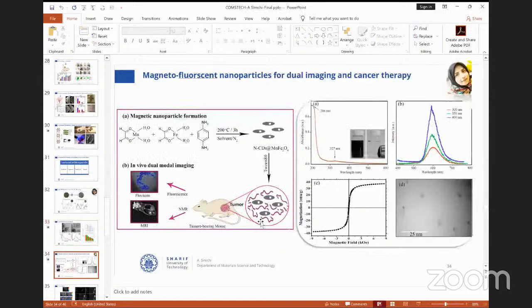Therefore, we tried to make another possibility, to make it targetable. It's very important. So we developed magnetofluorescent hybrid particles that can be used not only for magnetic imaging, but also for fluorescent imaging. So this is a dual imaging for cancer therapy. One of my postdocs developed a special in situ procedure to prepare magnetic nanoparticles covered by a thin layer of graphene on the surface, or decorated by graphene nanoparticles or graphene quantum dots on the surface. Then after preparation, she covered the surface with a polycarbonate polymer in order to incorporate drugs and biomolecules inside the polymer shell.